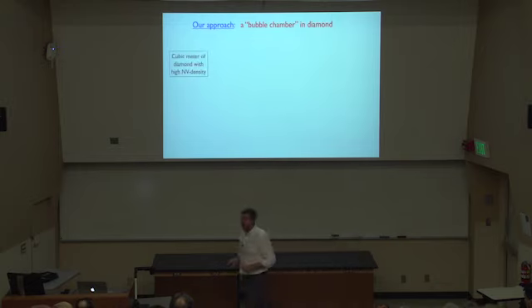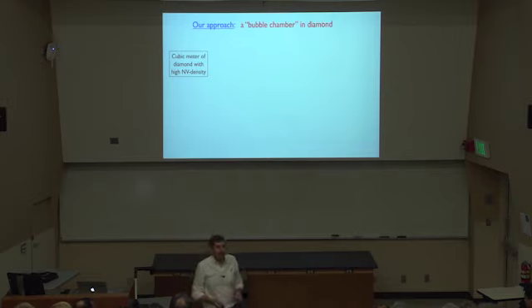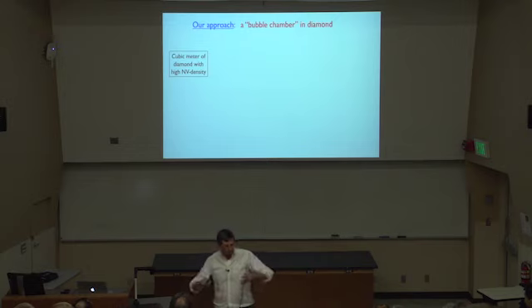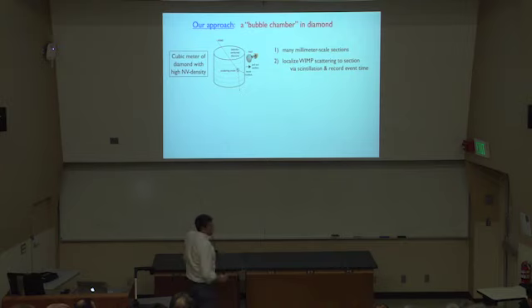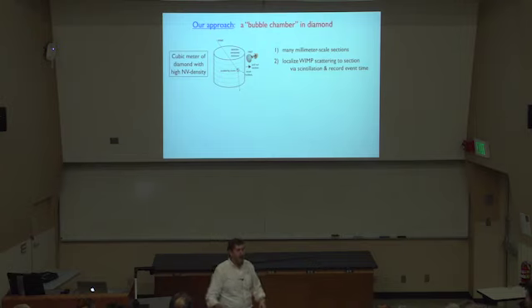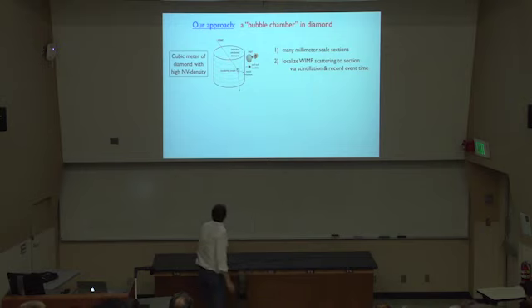All right? A cubic meter of diamond with high NV density inside of it. It does not have to be one giant cubic meter of diamond. You need the cubic meter to get enough mass, right? It can be broken up into many millimeter scale sections, either slices shown in this simplistic cartoon or little smaller sections. Diamond is known to be a very good scintillation material. That means when and if there are interactions with WIMPs, and certainly with neutrinos, it will create very good scintillation light, and you could localize the event with traditional detection to, let's say, a cubic millimeter.